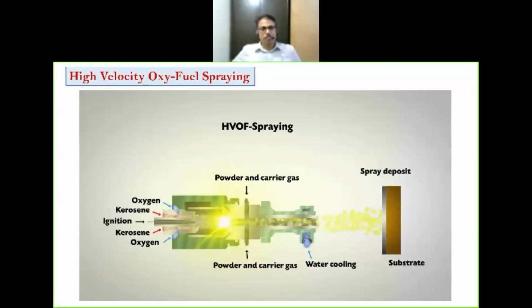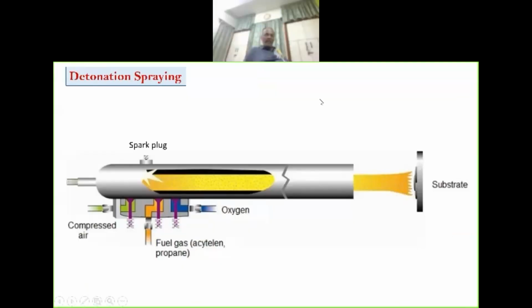So that is HVOF. Next, another one. We call it detonation spray. What is that? We have a tube. Inside the tube, we have installed a spark plug. We push in fuel gas and oxygen and start exploding it at a rate of 2 to 4 Hertz. It explodes, high temperature and pressure generate, powder particles inside are taken afloat by the expanding gas and carried to the substrate. Once again, a very dense coating, but it's a metal coating, not meant for oxide. Also, the process is noisy and a little bit hazardous, and it's not available commercially. One must go to a designated job shop to get it done, but it's a very good process for metals.